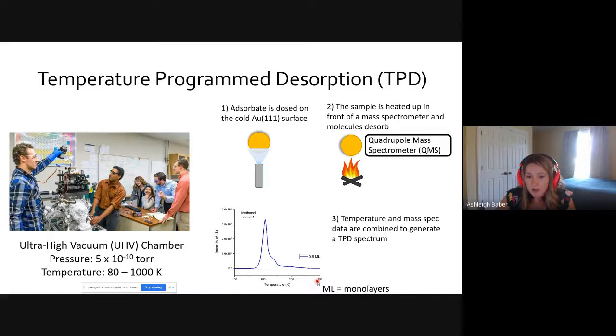Well, in order to maximize the signal, what we've done is, as you can see, we have a very large manipulator on our chamber so that we're able to move pretty far in any given direction within the chamber. And so for our experimental setup, we have a Hiden HAL 3F for our mass spectrometer, and it's covered with a shroud that has a small aperture on the end. And then we bring our sample just as physically close as possible to that aperture, so the aperture is right in the middle of that gold surface, to try and maximize that signal to noise ratio. Does that answer your question?